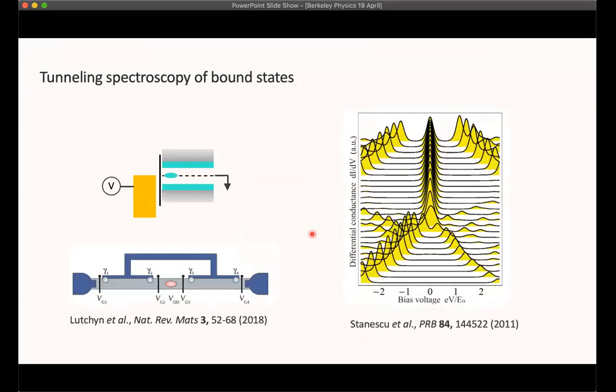Another important note, particularly for systems where you're suspicious that Majorana quasiparticles might be lurking, is that this junction spectroscopy should be sensitive to the presence of zero energy states. So I'll remind you that these Majorana quasiparticles that we predicted should be pinned to zero energy because of particle-hole symmetry. So simulations predict that what we should see is not only a gap in the density of states, but also when we're in the topological regime, a peak at around zero bias in the spectrum. So that's something we can look for, for example, at the ends of wires. We can attach a tunnel junction and look for a peak at zero bias to tell us that there should be Majoranas present.